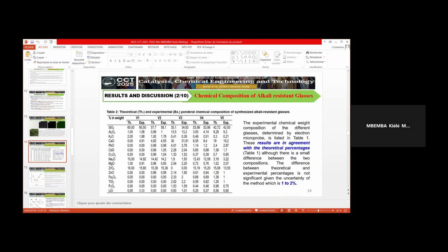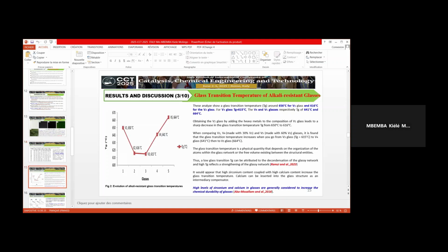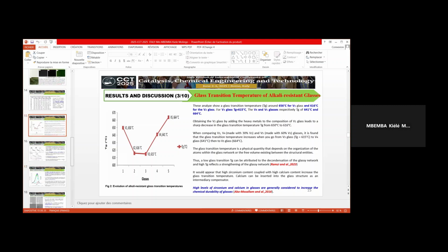Concerning the chemical composition of alkali-resistant glasses, we can see that experimental results are in agreement with theoretical results. The difference between the two results is not very significant, because the uncertainty of the method is 1 to 2%. Concerning glass transition temperature, we can see that all 5 glasses are at a temperature around 600 degrees Celsius.